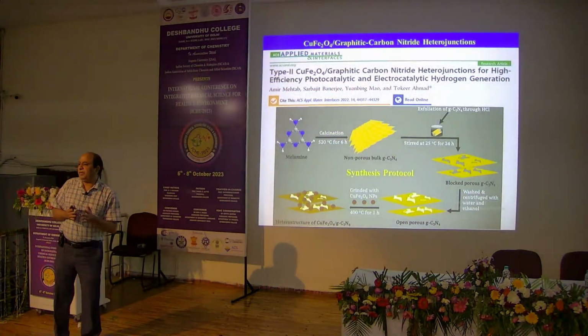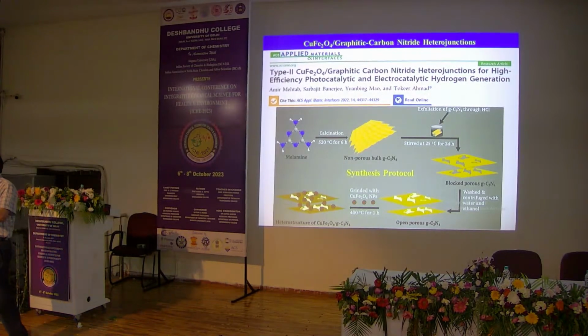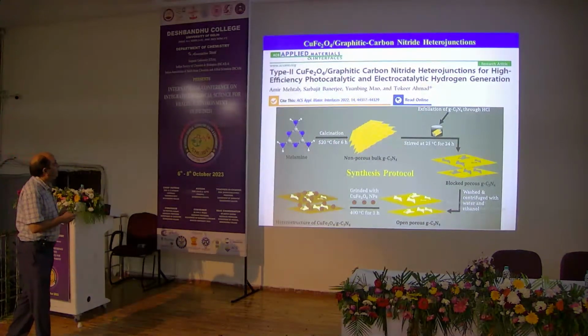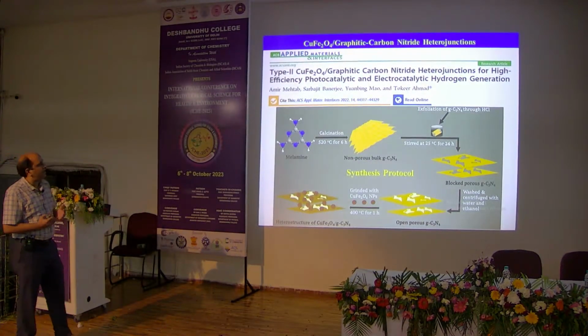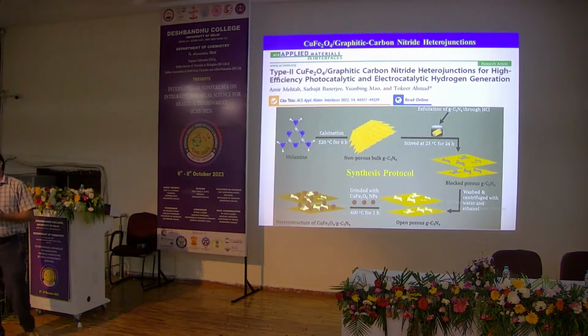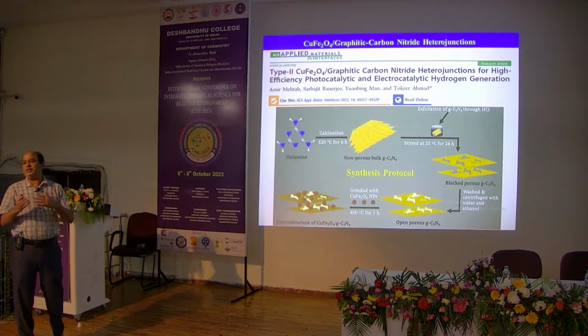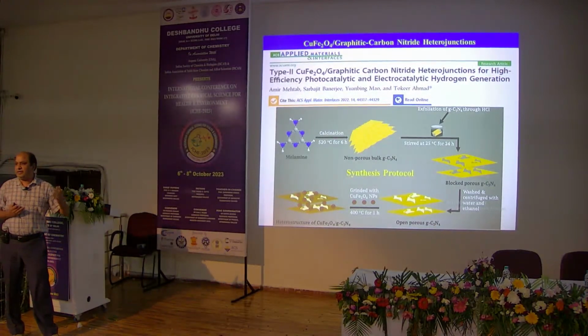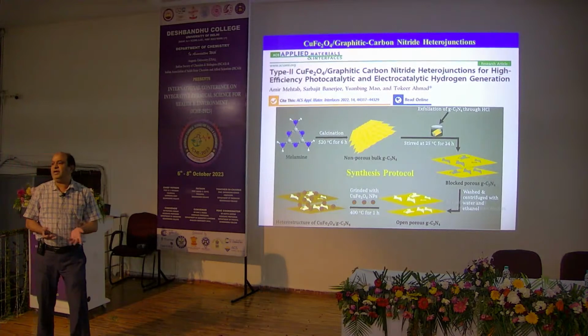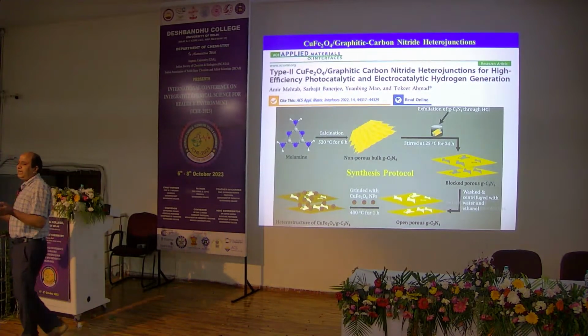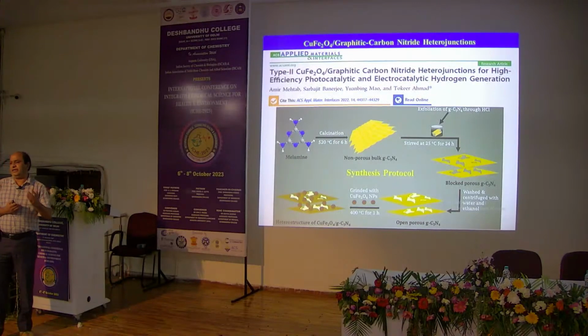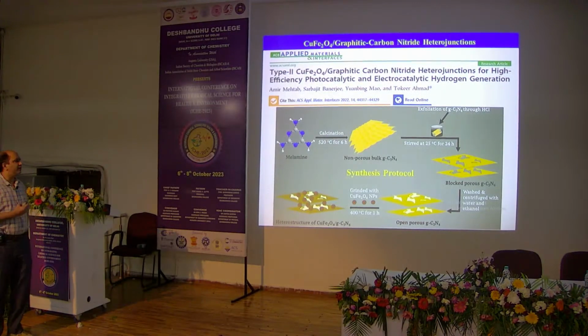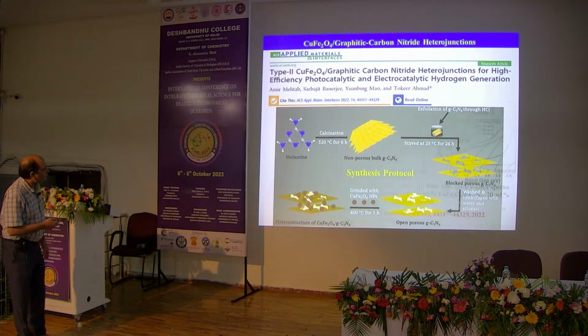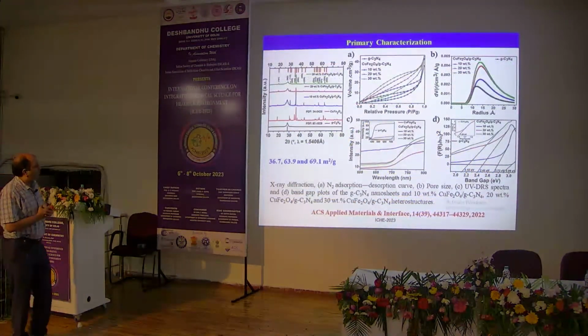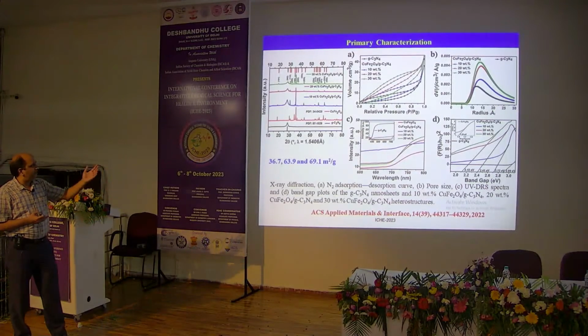Then these as-prepared graphitic carbon nitride nanosheets were used to design heterostructures with copper ferrite. So we have prepared type 2 copper ferrite graphitic carbon nitride heterojunctions and applied them for the photo and electrocatalysis reactions. The methodology was simple. Initially you prepare the graphitic carbon nitride as I have discussed earlier, and prepare copper ferrite by a simple hydrothermal method, and mechanically mix them in different weight ratios like 10, 20 and 30 weight percent. We have taken three compositions.